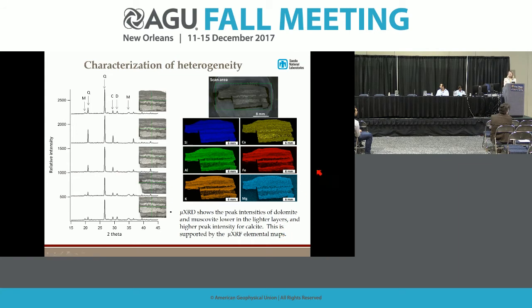Going back to the issue of heterogeneity, as I mentioned before, mineralogically these layers are similar. There are no phases present in the lighter layer that aren't present in the darker. But when we use microfocus X-ray diffraction, we can see subtle differences between compositions. As we move from the darker layer into the lighter, we see an increase in calcite and quartz. So it's more quartz and calcite rich, and the darker layers are more illite, muscovite, and dolomite rich.